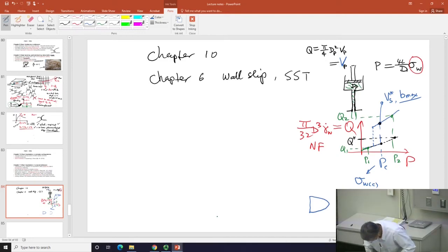So remember, what I drew gives you a sense of the shear rate that dropped, and gives you a sense of the stress that dropped. And that stress could now be below the hysteresis stress. So the system will come back to stick. Meaning from wall slip, come back to stick, because that's the boundary. That's the condition for stick.